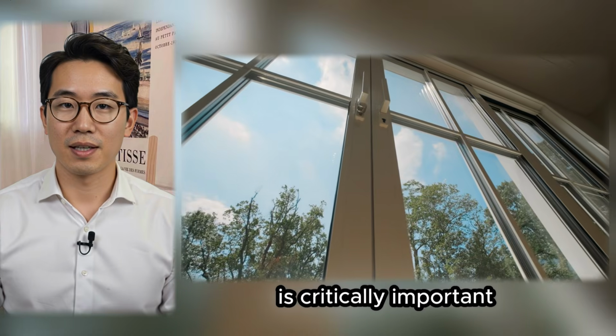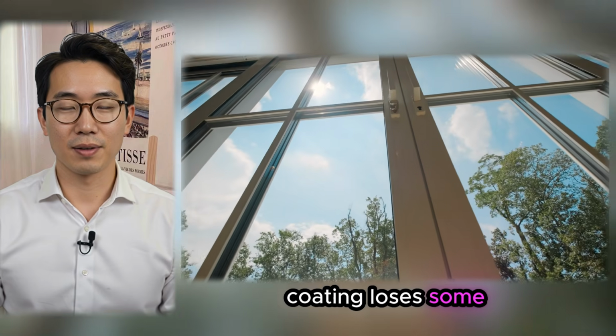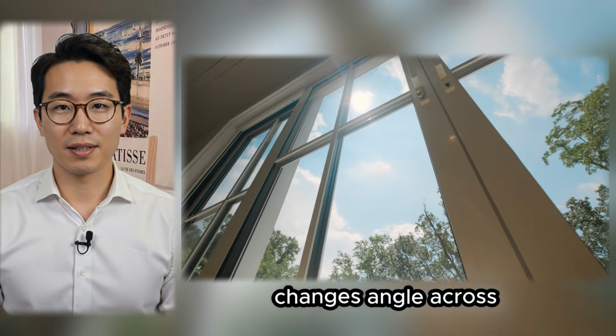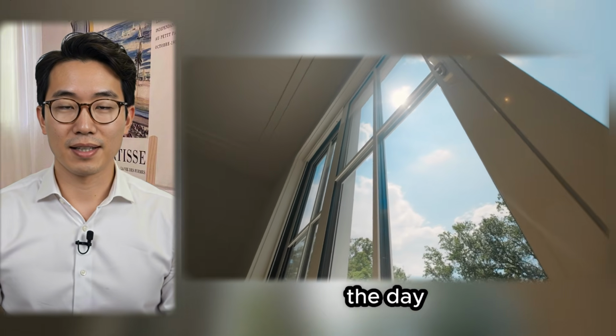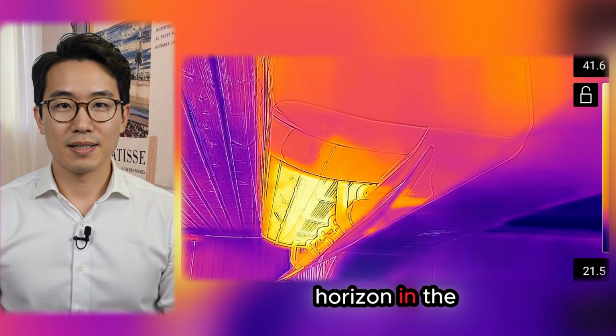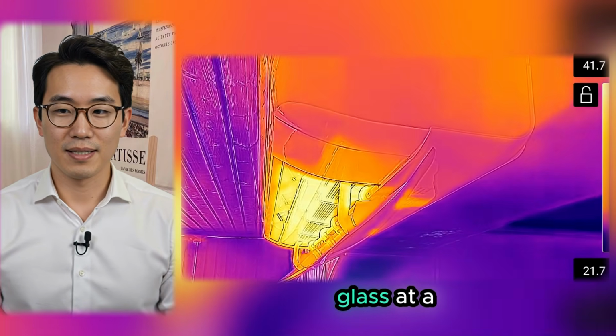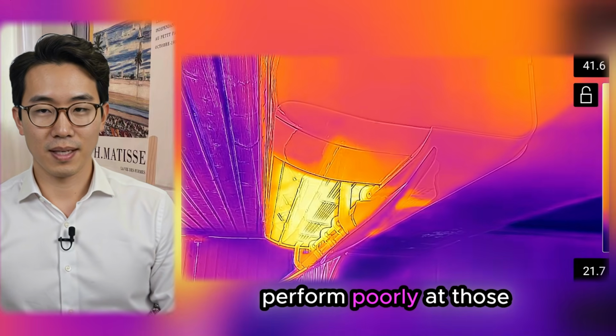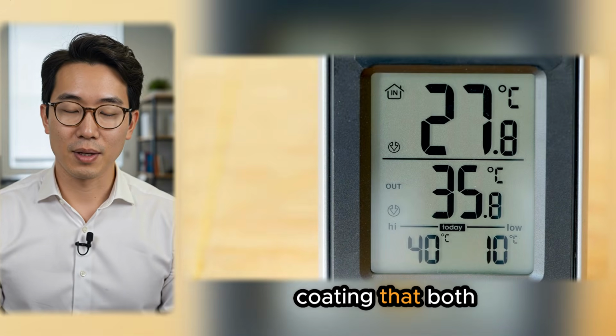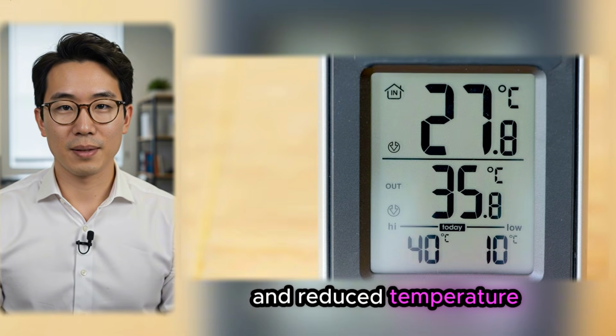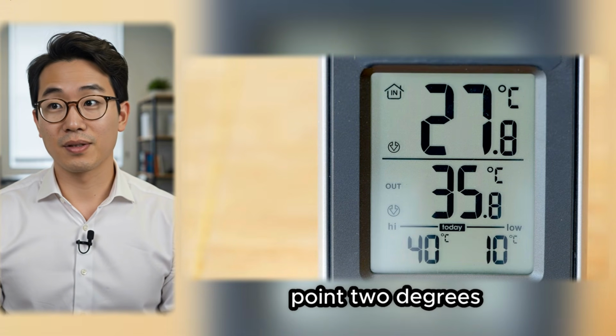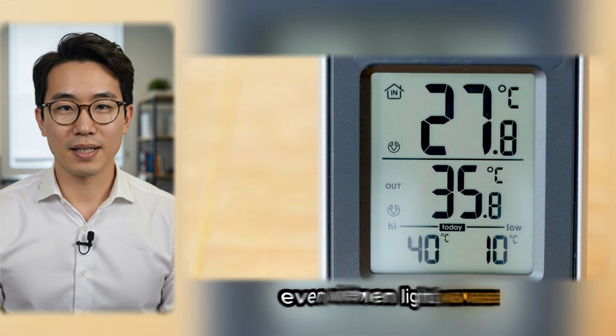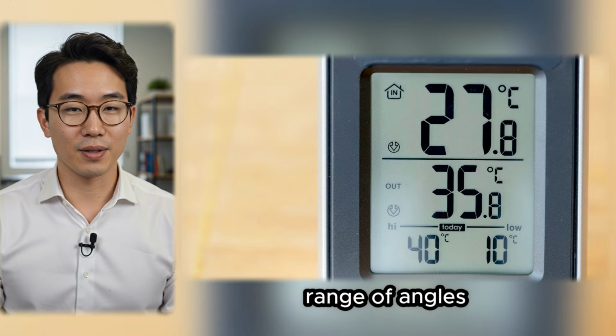That last part is critically important because almost every window coating loses some of its effectiveness as the sun changes angle across the sky throughout the day. When the sun is low on the horizon in the morning or evening, light hits the glass at a steep angle, and many coatings perform poorly at those angles. Their model produced a coating that both maintained transparency and reduced temperature by 5.4 to 7.2 degrees Celsius in a model room, even when light was transmitted in a broad range of angles.